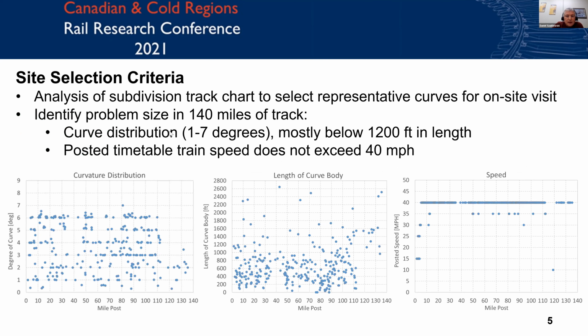So we then started looking at what we can do if we go out to track, and what types of curves we should be focusing on to find out how widespread the problem of those types of rail in track is. So we were looking at 140 miles of track. We looked at the curve distribution first. We saw that the curves range from tangent rail to the 1 to 7 degree range for all the curves in this 140 mile territory.